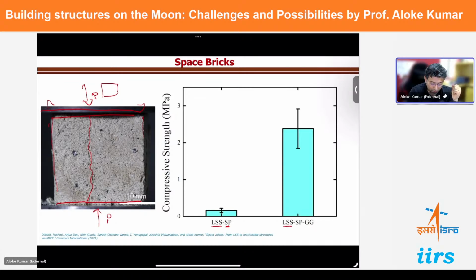Now we added on the lunar soil simulant, we had the bacteria, and we added this bit of guar gum, right? And when we tested that, we found that the compressive strength was of the order of 2.5 megapascal to almost 3 megapascal. Now, just to put this into perspective, ice is of the order of 5 megapascal, sometimes higher, depending on the temperature, around 5-6 megapascals. So 2.5 is not bad. It's almost like half of ice. And with ice, you can make igloos, right?